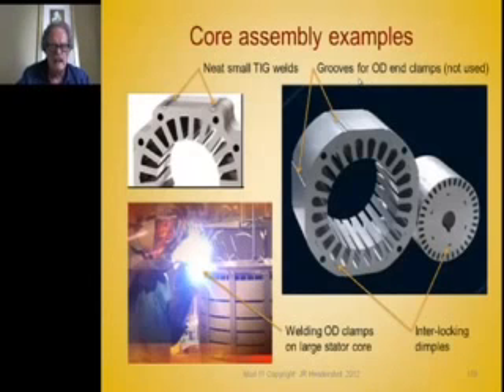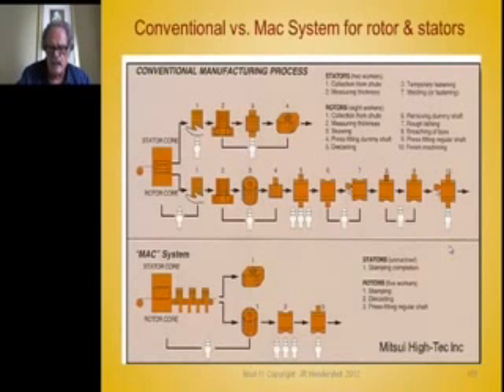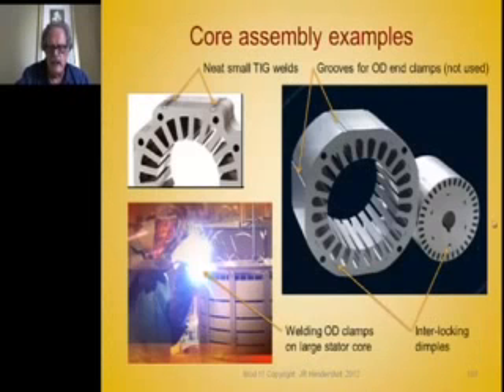Here are some nice pictures of the interlocking of the laminations that I showed you two slides ago from this Mitsui High-Tech. This Max system gives you laminations like this, where right in the die, when you're punching the slots and notches, you punch these little dimples that nest each other from one lamination to the next and make a beautiful stack that comes right off the die. There's no labor for that. And it's very accurately aligned. Everything is aligned perfectly because it was all tooled in the die.